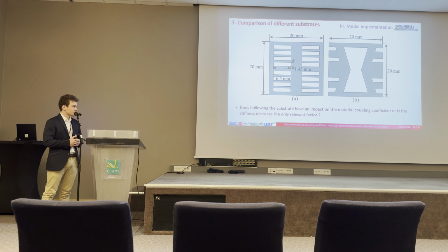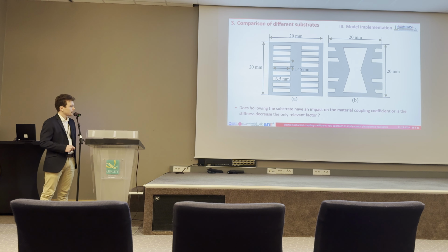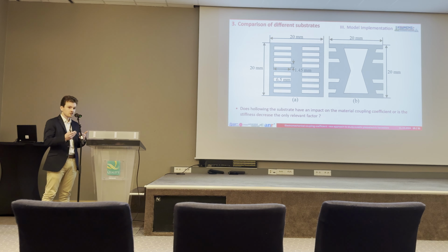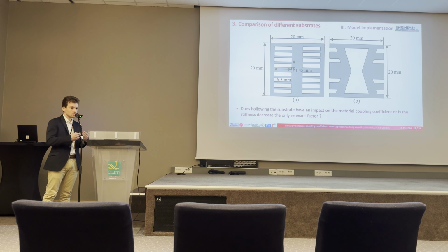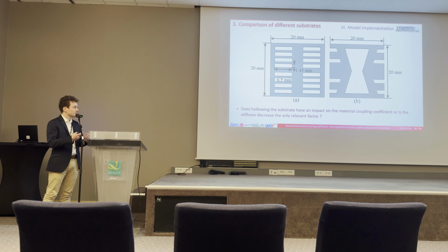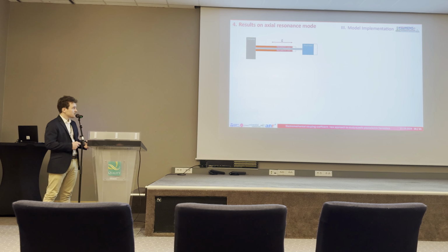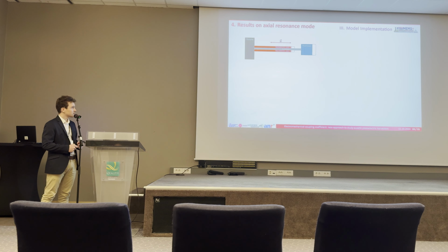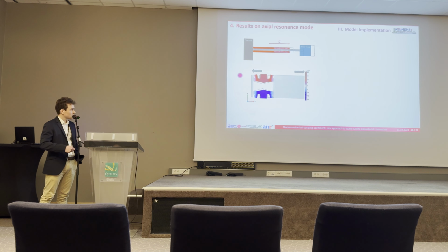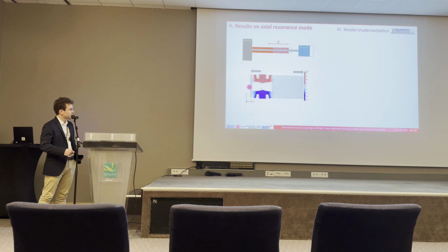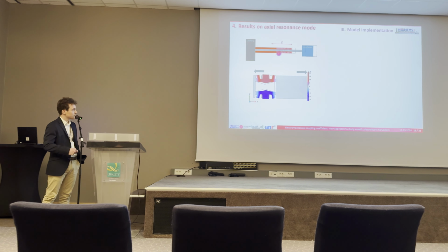Let's now work on some auxetic substrates. Here are two substrates. One is just hollowed out, and one is auxetic. They have the exact same filled area. So this is to know if the performance change is only due to stiffness decrease, meaning frequency decrease, so better power. Here are the results. So first we studied the axial mode resonance. As we can see here, with the auxetic property, as we have expansion, we expand laterally.